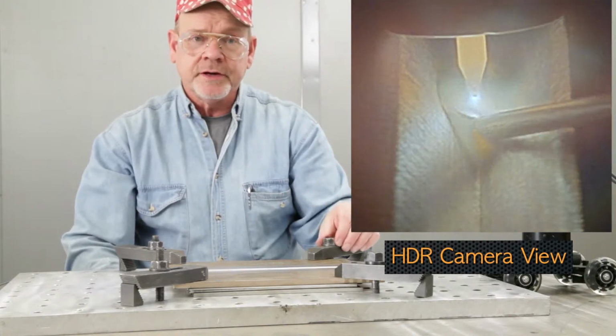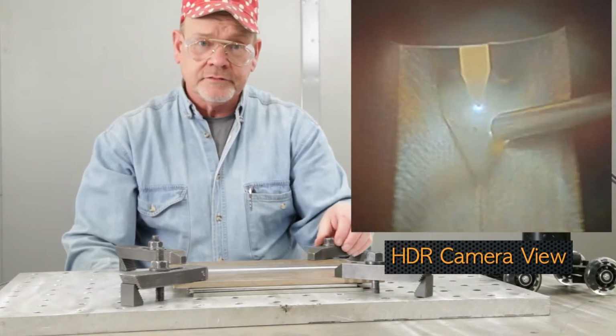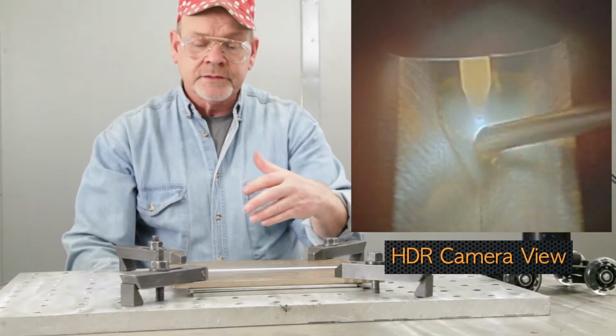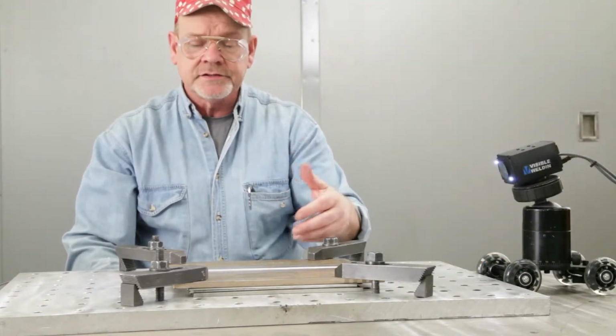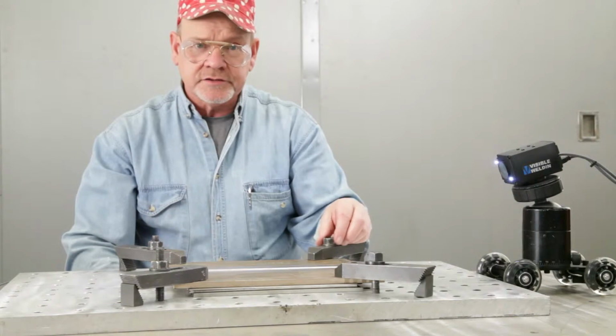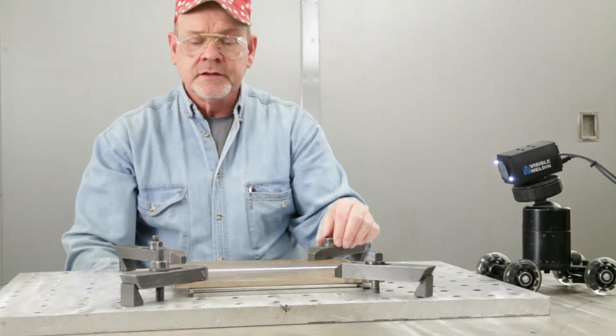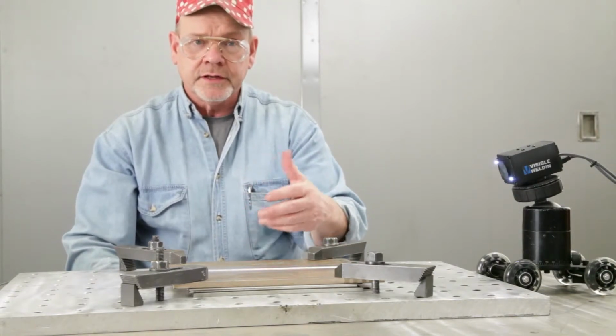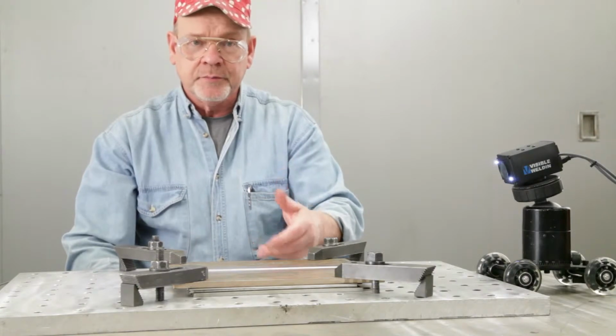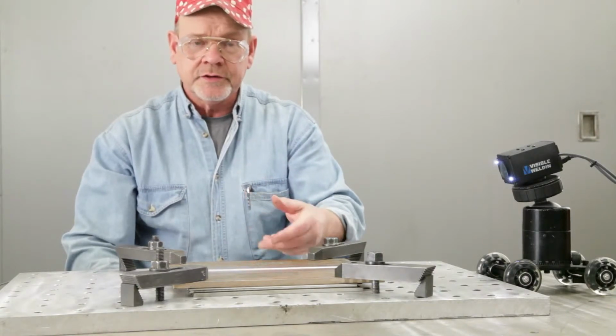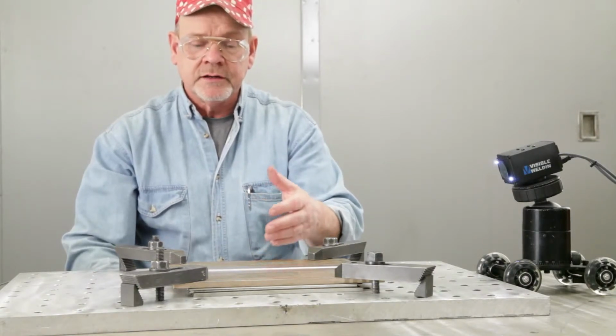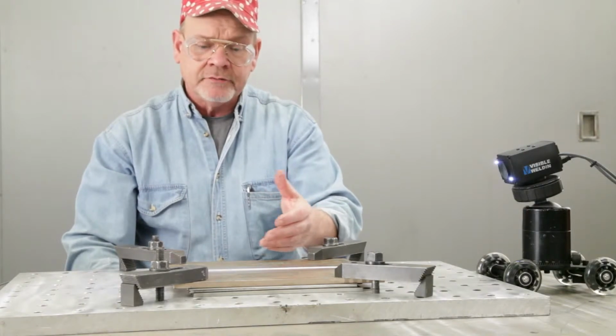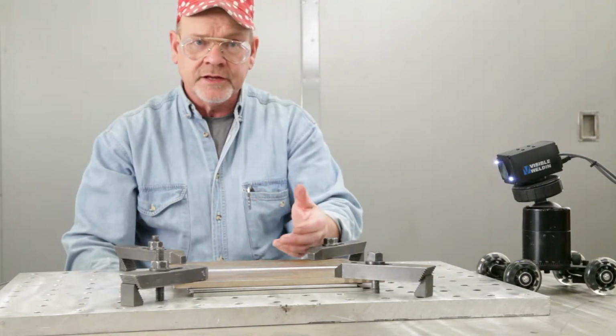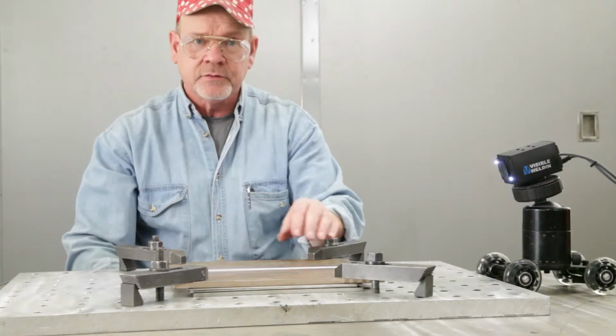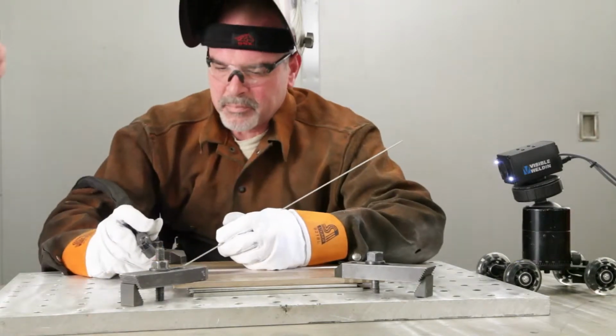It's important to remember the fluidity of copper-nickel welding, similar to other nickel-based alloys, is much more sluggish than it is with carbon steel or stainless steel, and therefore puddle control and wire feed is very, very important. In addition, with copper-nickel alloys, we want to be sure that the wire never gets out of gas coverage from the gas cup, and we'll show you all that as the welding progresses. We're ready to start welding.